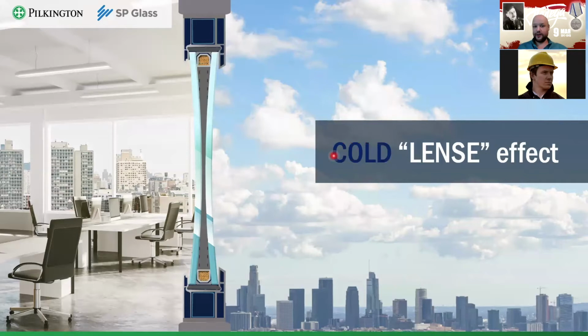In Russia, usually we have the very opposite of that. That is called a cold lens effect because of the cold climate. In the winter, it is cold, gas is shrinking, glass are moving closer together up to a point that in certain IG units, they can touch each other in the center of an IG unit, creating a lot of visible defects in this central area. But we will not be talking about this now.